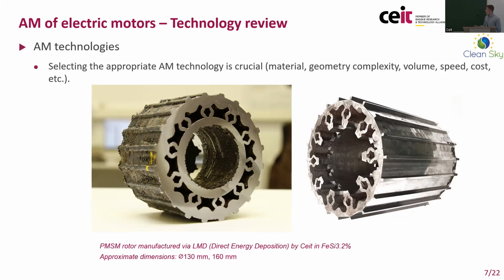You can see that even if the part is dense and has no apparent porosity problems, and has quite good mechanical properties in this case, when manufactured by laser metal deposition the surface quality is quite poor, and quite some machining effort was required to get the final rotor geometry. So what I want to stress is that not only material properties and material processing are important, but also selecting the technique most adequate to the part you need to manufacture.